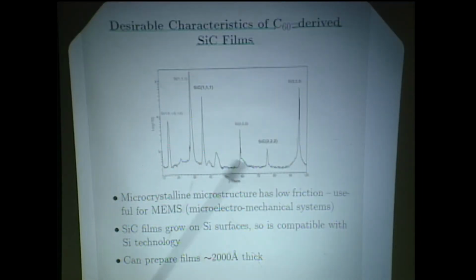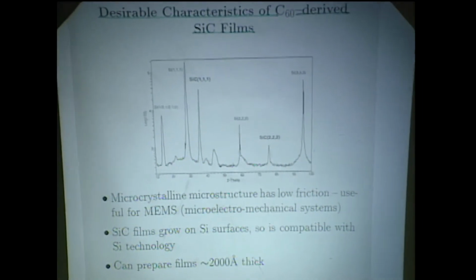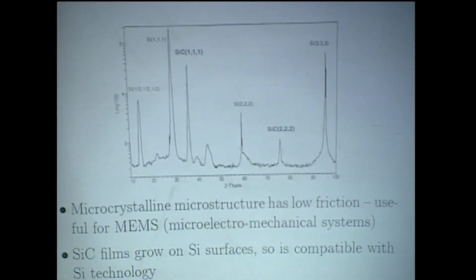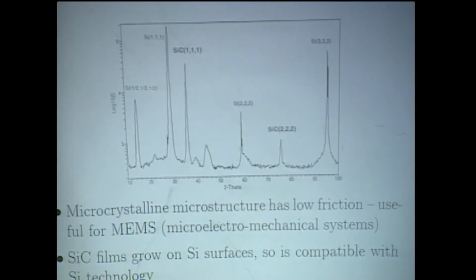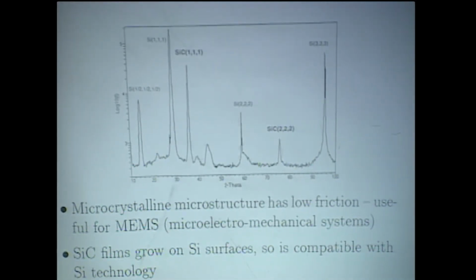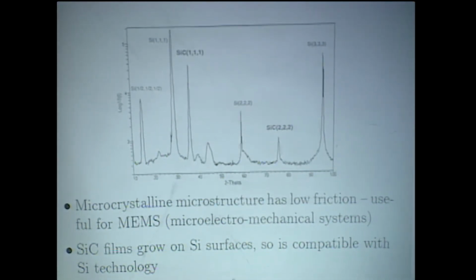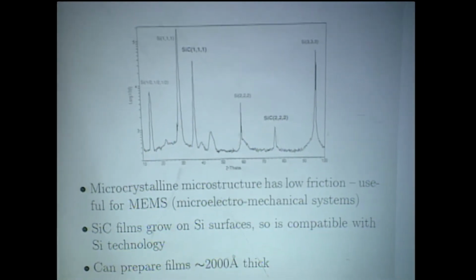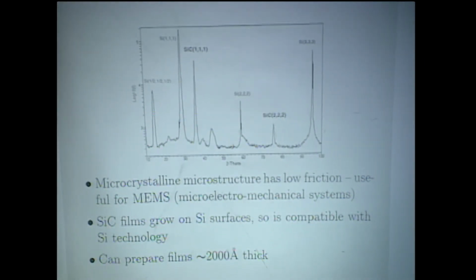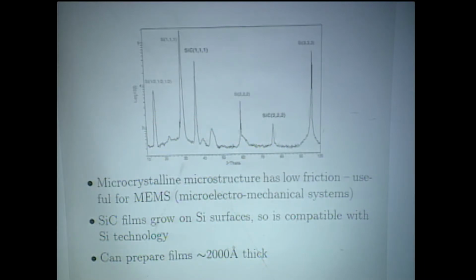So this is a way, and it's been done now in quite a number of labs around the world. Right now it is in universities. There's no practical device yet, but I think there could be. And this shows you that it's single crystal, and here are the reflections for cubic silicon carbide. It has very nice frictional properties, so people in MEMS, in micro mechanical systems, might find this a good system. And you can prepare films up to 2,000 angstroms, which is about as thick as you want to go for device applications. And there may be other things that you can do with the buckyballs.